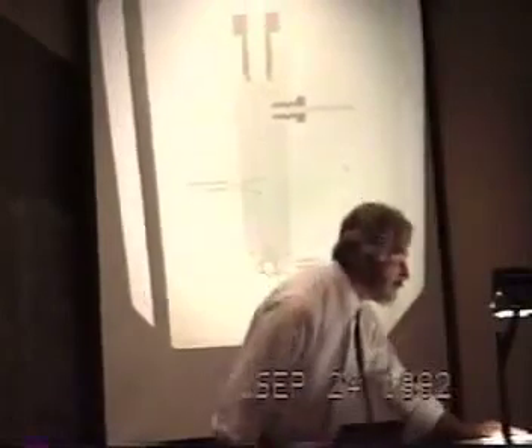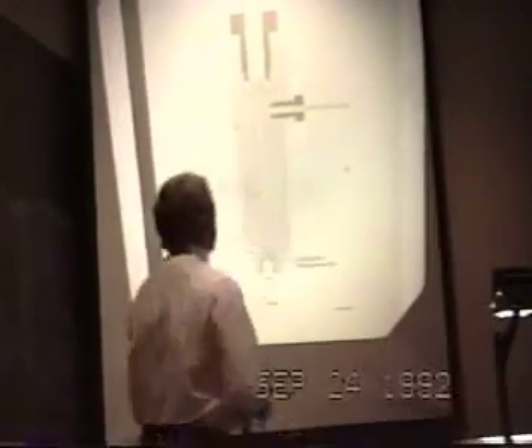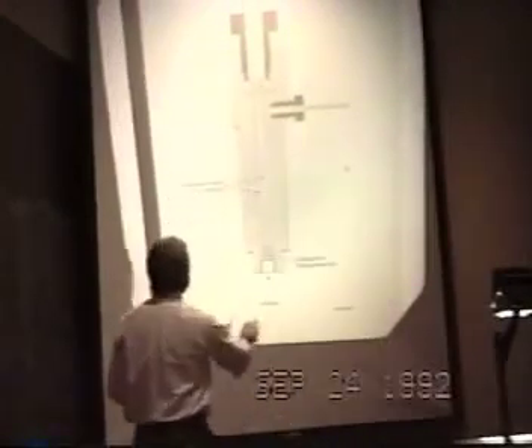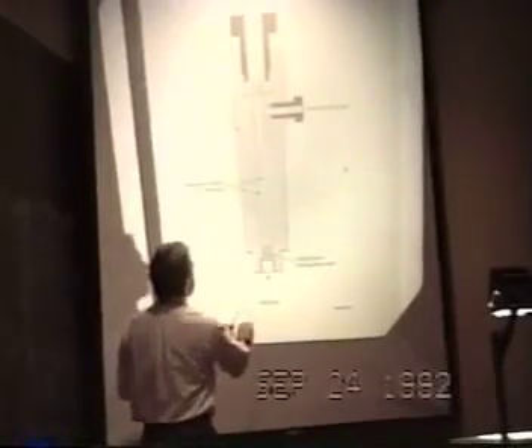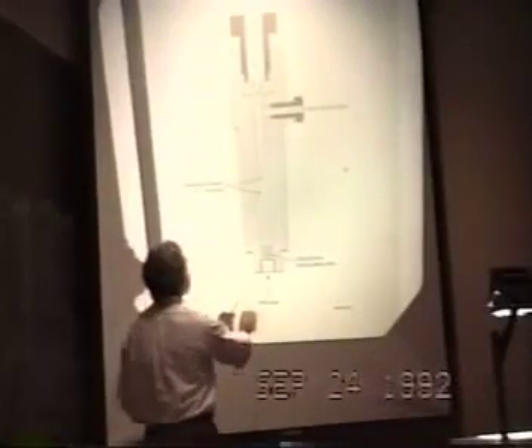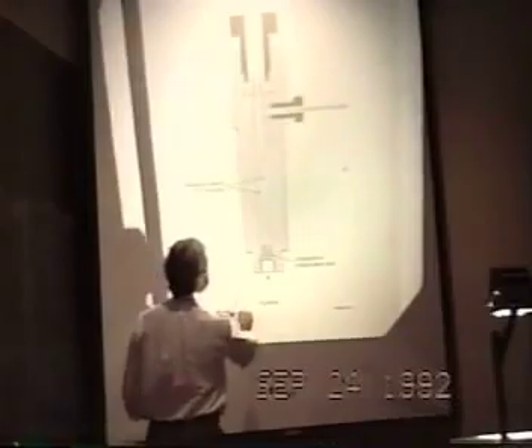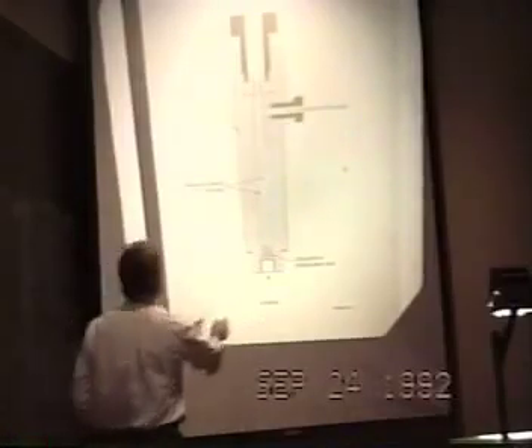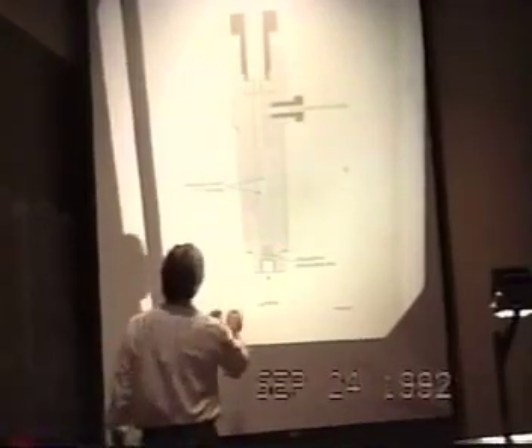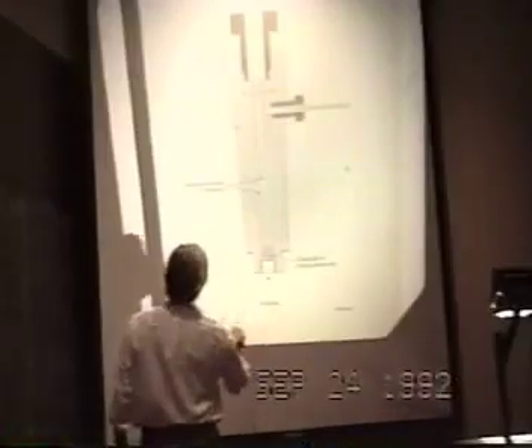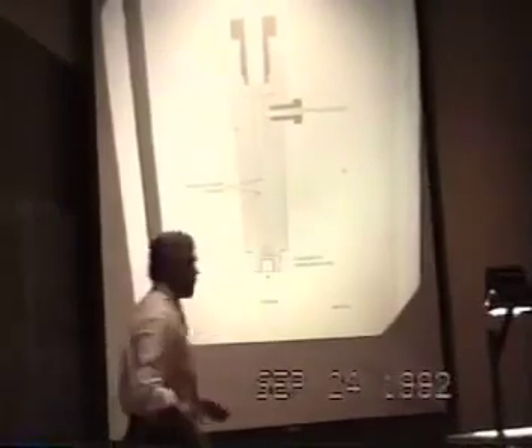One of the very important things that you must do is ensure that the temperatures that you measure are accurate representations of the average temperature of the flowing fluid. You must well mix the fluid flow, particularly before the outlet sensors, so that you measure a good average temperature. Here's the outlet temperature manifold, 2 temperature sensors, and the fluid flow. I'll show you the fluid flow path.